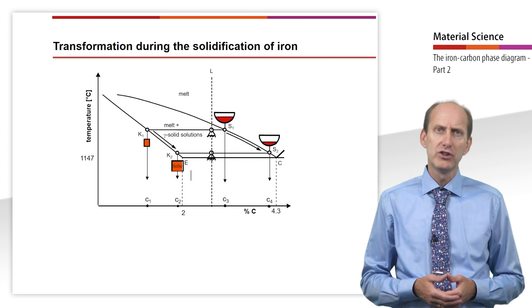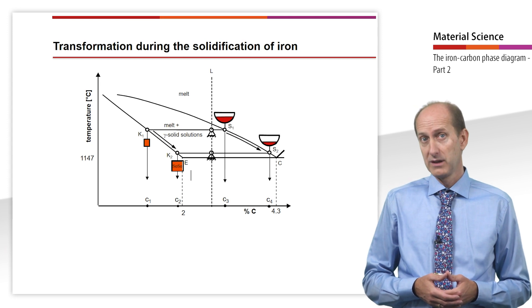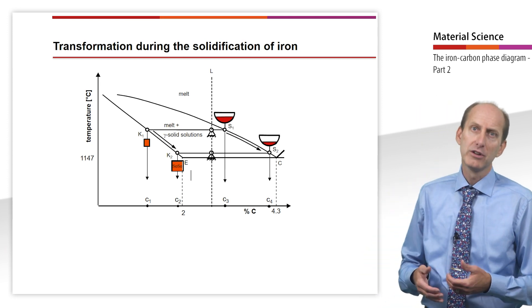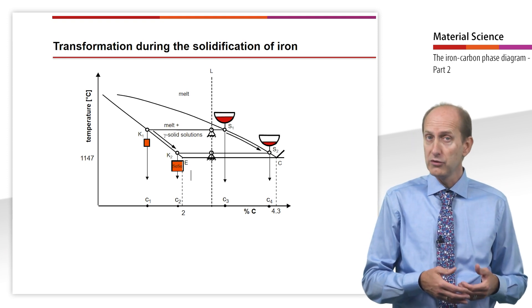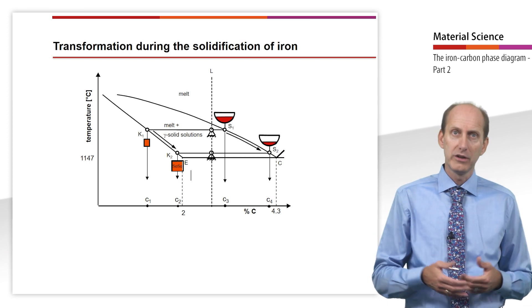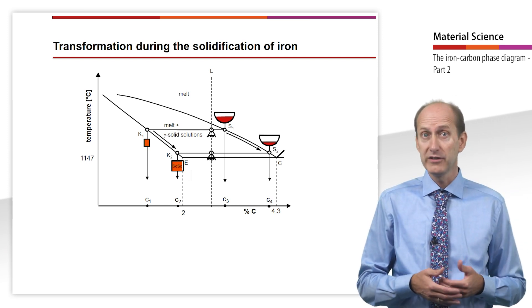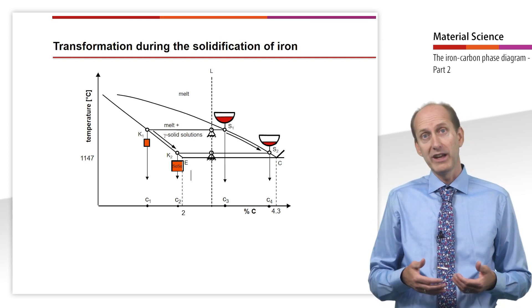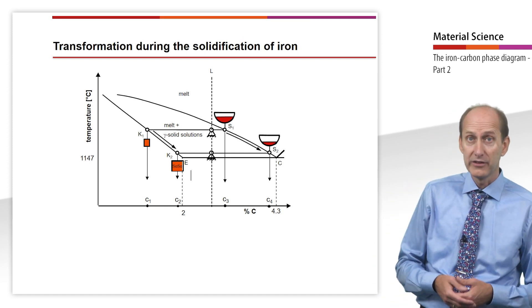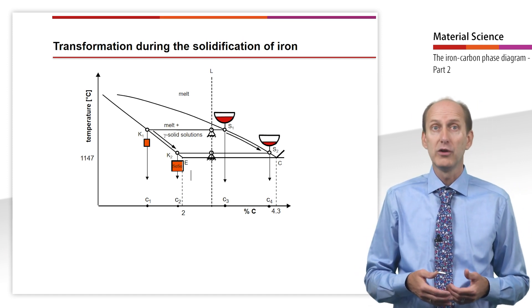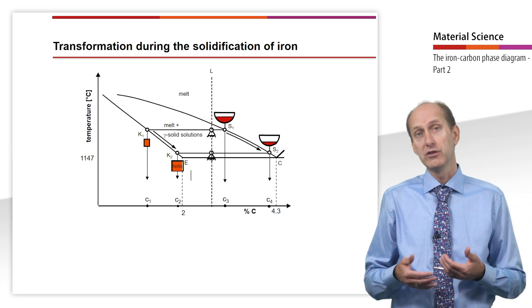These crystals become richer in carbon content due to increasing formation. In the example shown here, the carbon content has already increased from C1 to C2. On complete solidification, the microstructure consists of homogeneous gamma solid solutions — that is to say, austenite. These crystals are interstitial solid solutions with carbon dissolved in the interstitial positions of the face-centered cubic iron lattice.